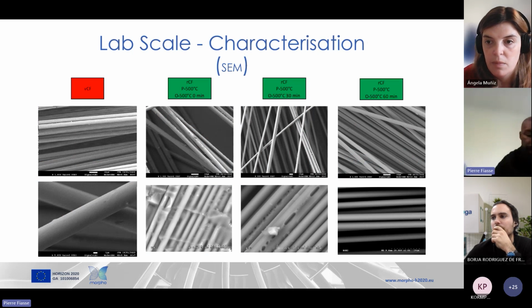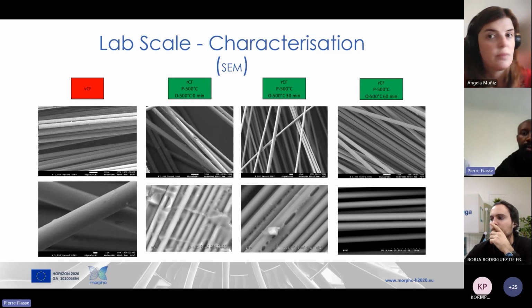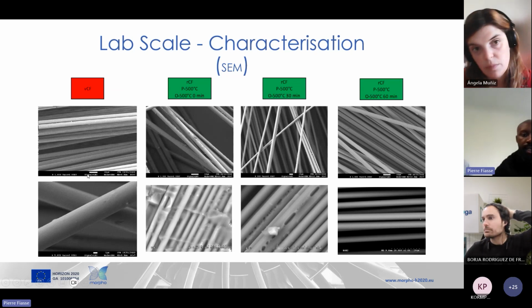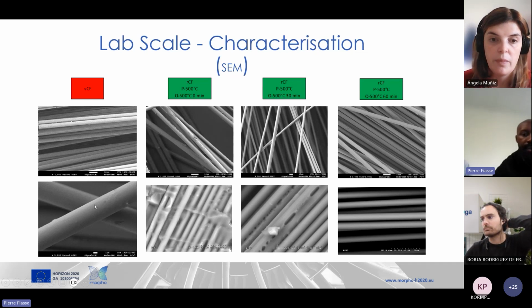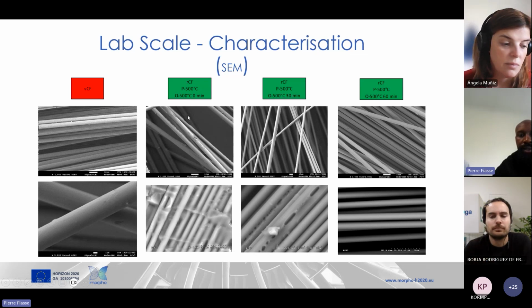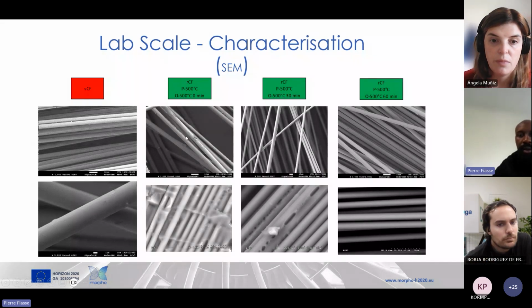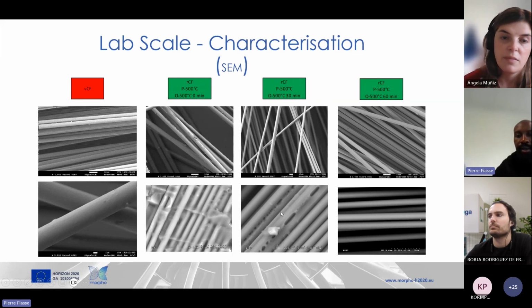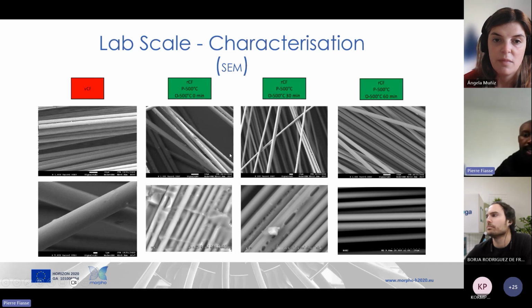So after the test, we made the characterization. We made two kinds of characterization, a microscopic one and then mechanical ones. On this slide, if you have a view of the virgin fiber, we can see that the fiber is quite clean. And for the rest of the images, we can see the fiber with dirt and the resin remaining on the surface of the fiber. The more we increase the residence time of the oxidation, from 0 to 30 and 60, the more we can see that the resin is removed from the fiber. We can clearly see the influence of the oxidation on the surface of the fiber.